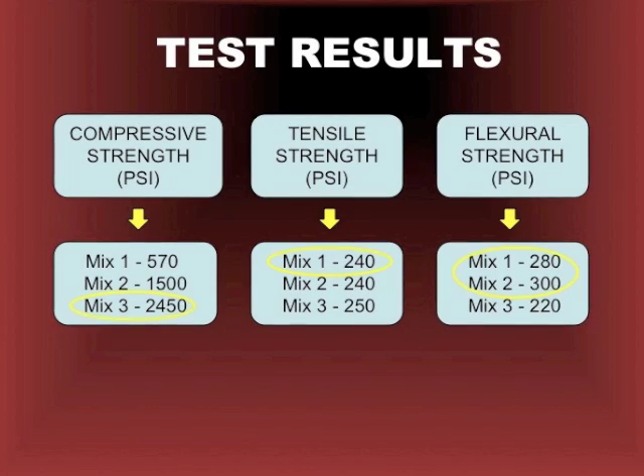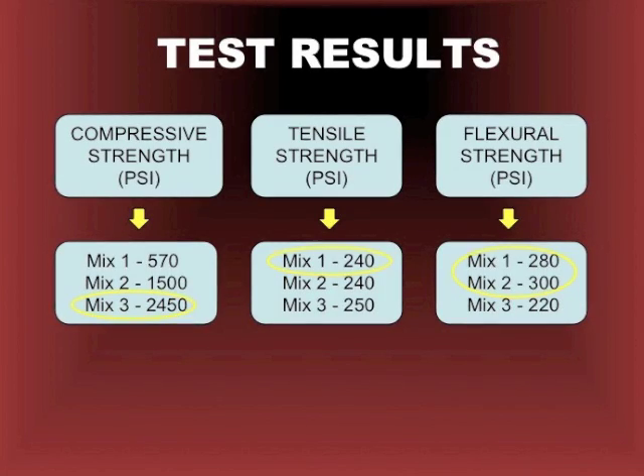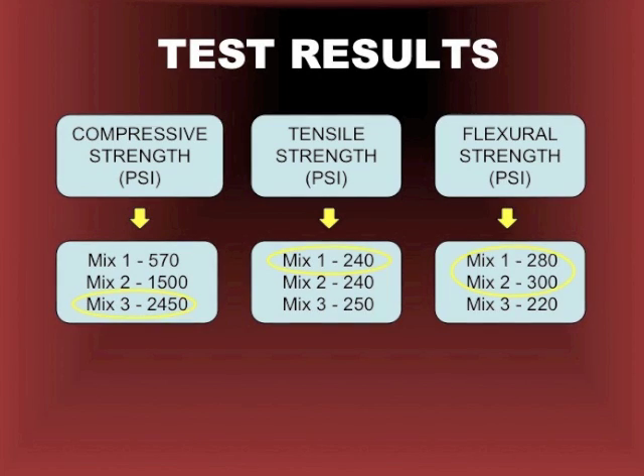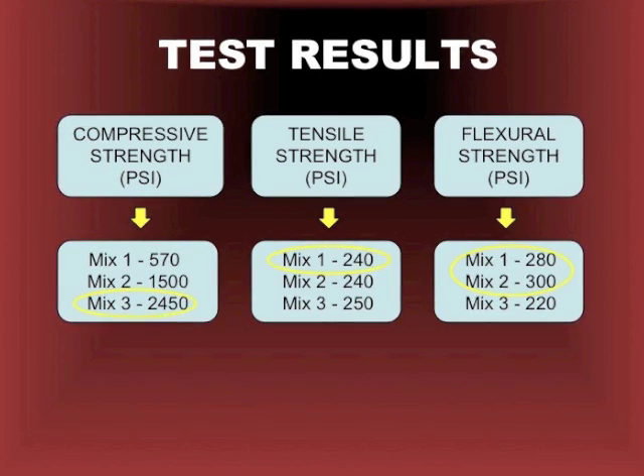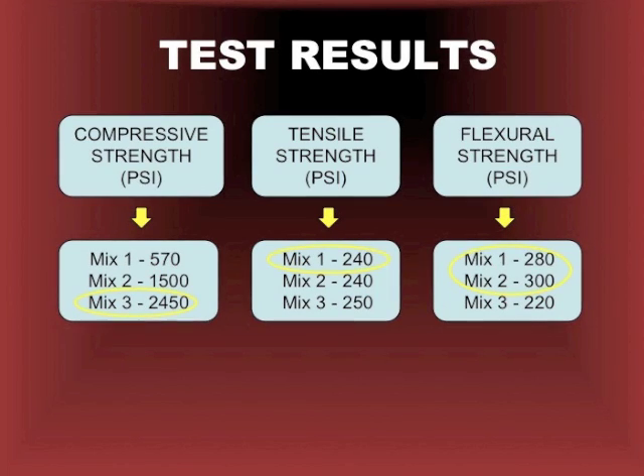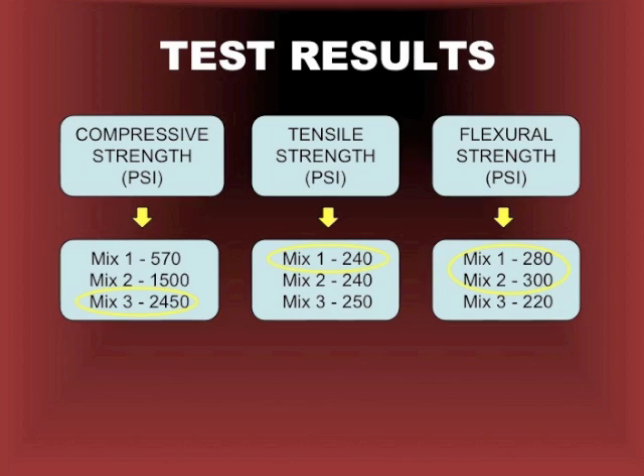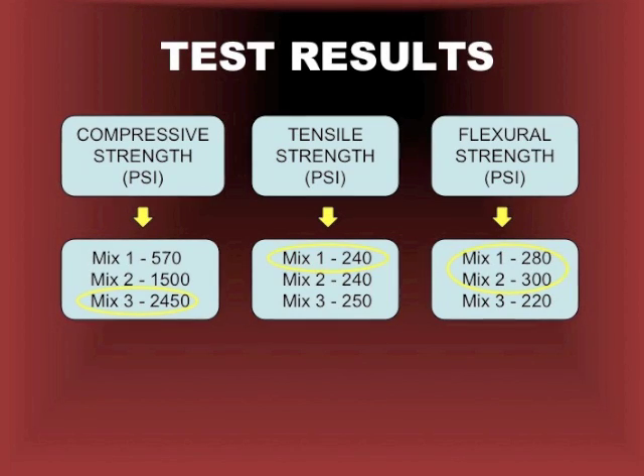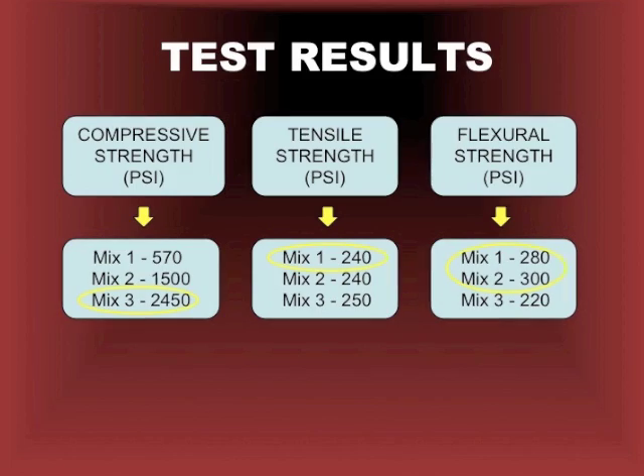Mix 3 had the best overall results. However, despite a poor compressive strength, Mix 1 was up to par in tension, which we believe could be because of the addition of the PVA fibers. Also, we believe the addition of the latex admixture in mix 1 and 2 resulted in a better flexural strength.